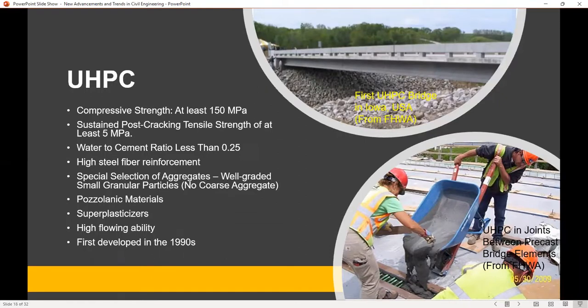This has also high steel fiber reinforcement. Now, these are not bars, these are little steel needles. Some of them have bent ends so that they are mixed in the concrete. And that is what gives you that additional tensile strength post cracking, but it makes it more difficult to mix. Okay, there is special attention to aggregates. There's no coarse aggregate or gravel used, only fine and very fine materials. Pozzolanic materials are used in there. Small granular materials used there. As I mentioned, chemicals such as superplasticizer are used there so that you get high flowability of concrete.